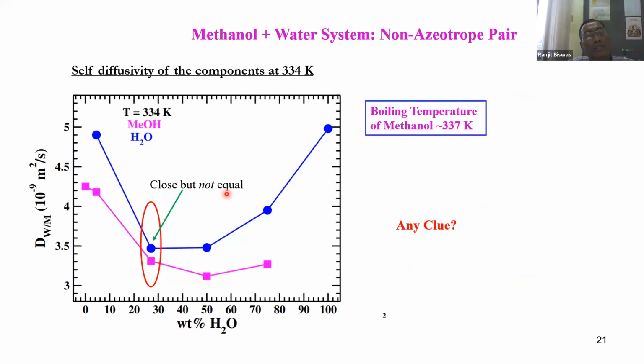So this is a very initial result. My collaborator Pradeep, who is doing the simulations, sent it to me just 2 days back, and what we see here is that they're pretty close, but not equal. The temperature that we have chosen is 334 Kelvin, and the logic of choosing this temperature comes from the boiling temperature of methanol, which is 337 K. Also, for the ethanol water system, the azeotrope forms at 351 K, which is a couple of degrees below the boiling point of ethanol. So we thought, okay, take this system near the boiling temperature of the alcohol and look at whether there is any equalization of component diffusion coefficients. And we don't see that.